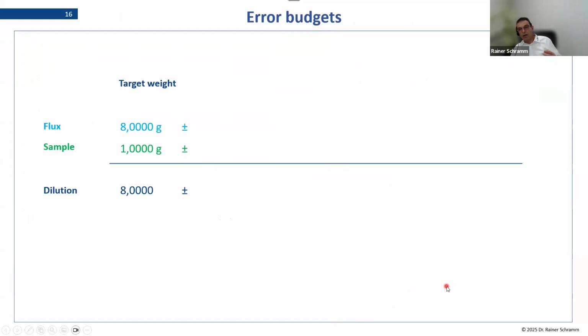Okay, let's put together our error budgets. First of all, we have our target. We want to weigh 1 gram sample and 8 gram flux, and of course we have a dilution factor of exactly 8. The balance adds just a very low error of 0.3 milligram for the sample and 0.2 milligram for the flux, and the dilution is just 3 or 4 digits after the comma.